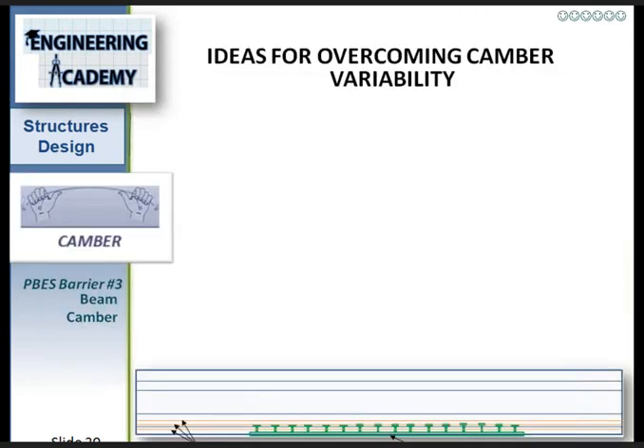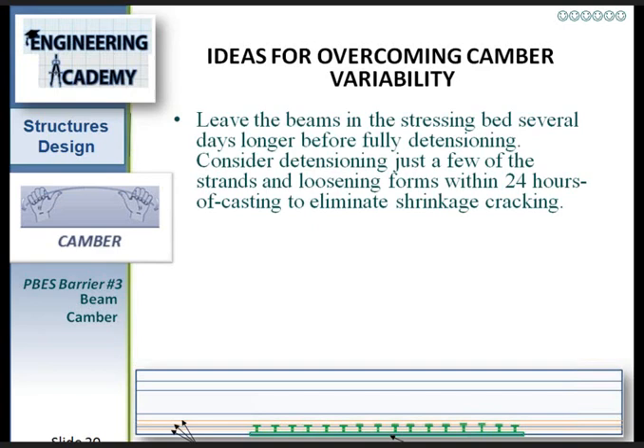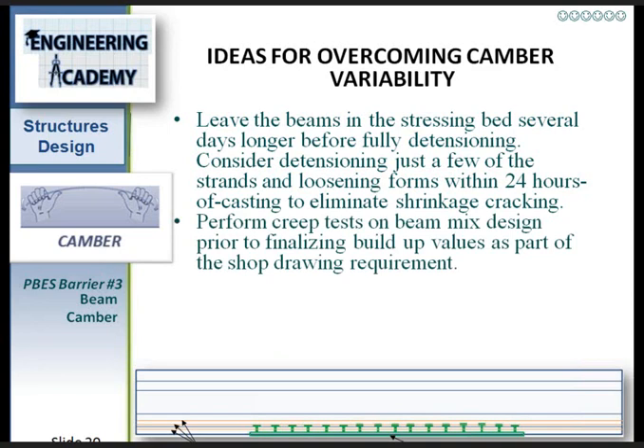Okay, so we talked about camber here, and let's throw out a few ideas of how to make camber more predictable. One idea is to leave the beams in the stressing bed several days longer prior to detensioning. Here you've got to be a little careful about leaving them in too long because you get shrinkage cracking, right? So you might have to worry about that. Another possible solution is to require a specialty engineer to perform creep tests of the actual concrete mixes used by the precaster, and then set buildups and pedestal heights based on the results of the actual precast yard turnaround times and mixes. I think that's a good one.